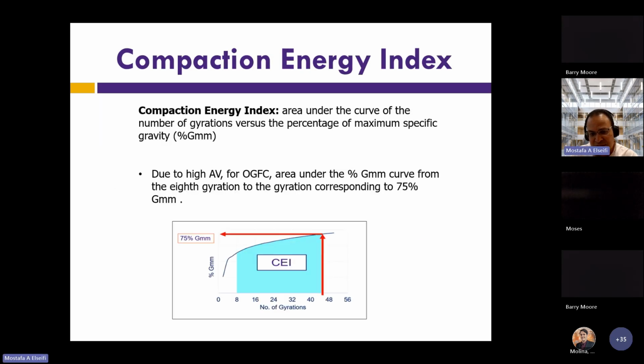The compaction energy index is measured based on the gyratory compactor. We plot the percentage GMM versus number of gyrations, and then we calculate the area under the curve, and this will give you how much compaction effort you should expect during the compaction of your mix in the field.